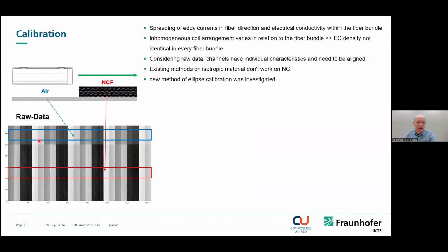Maybe somebody of you knows that calibration is a challenge on anisotropic material. On isotropic material it's not a big thing: you make a measurement in air and you make a measurement on the component. But here at the non-crimp fabric, the NCF, we see this behavior. Because of the high frequencies, we have electronic phase shifts and different amplitudes based on the connection of the array, so it's a daisy chain. And here we see the raw data in air and the raw data on the fabric. So typically you cannot analyze anything when you look at the raw data.